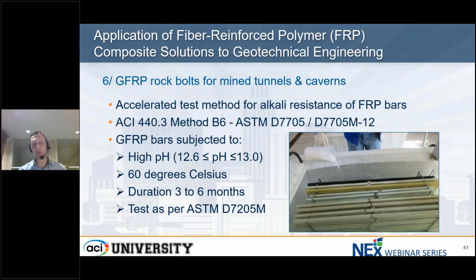Again, for those of you not familiar, this accelerated aging test is pretty straightforward. The idea is to conduct tensile tests as per D7205, as I showed earlier, but after conditioning the bar. So you get some test bars at T0, at 0 hour, but then you also want to have bars in an environment that is high temperature, so 60 degrees, and very high pH, and that will give you a simulation of the long-term behavior of the material.